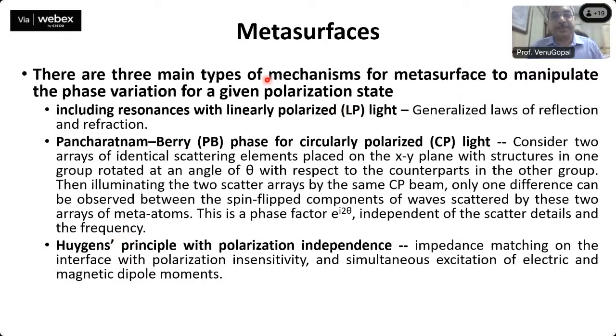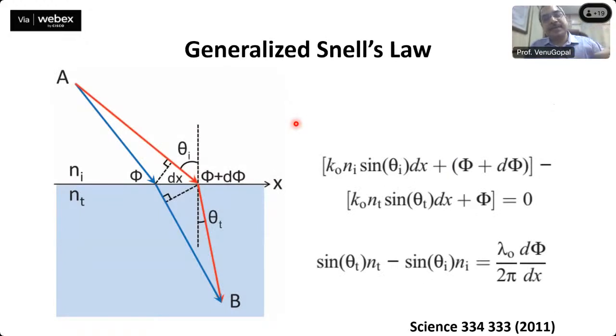So there are three main types of mechanisms where metasurfaces are used to manipulate the phase variation for a given polarization. So for example, you can take linearly polarized, circularly polarized, or completely polarization independent structures. Right. So each one is defined in terms of, for example, the linearly polarized case, or we can look at generalized Snell's law. For example, if you have a circularly polarized light coming at an angle, then instead of having a circular shape, at the point of incidence you'll see that it gets elongated slightly. So you'll have a certain phase difference from one end to the other end. If one is phi and the phase at the other end is phi plus d phi, and the spread of the spot is dx, what we can talk about is d phi by dx, which is the change in the phase across the beam position.